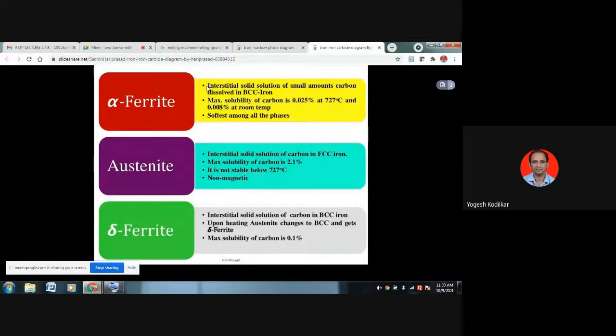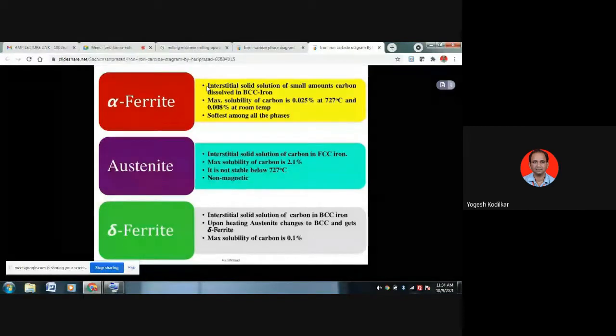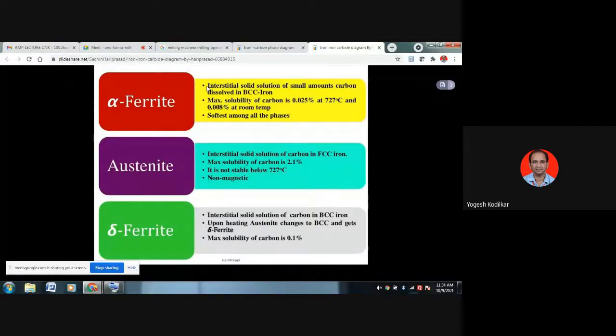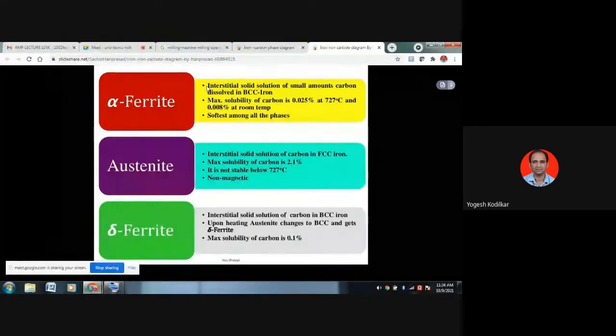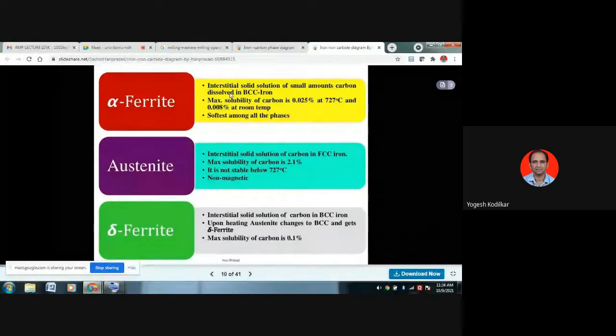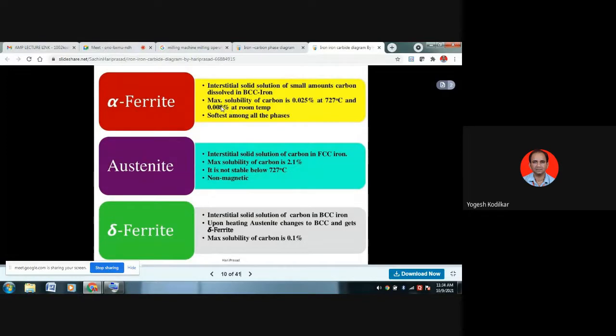Right. The initial phase at room temperature is the alpha ferrite phase, having an interstitial solid solution of small amounts of carbon dissolved in BCC iron. So the maximum solubility of carbon in the alpha ferrite phase is 0.025% at 727 degrees Celsius and 0.008% at room temperature. You will see that in the diagram also.